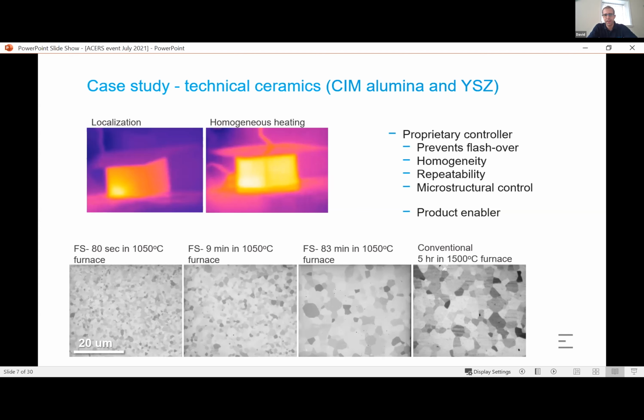But then if we start saying, we'll call it flash sintering, I suppose one could argue it's not flash sintering if you take 83 minutes, but in terms of the application of an electric field using our controller for 83 minutes at a furnace temperature of 1050, we get a comparable microstructure to the conventional one again, and that's consistent across the breadth of the sample there. Then as we go down to 9 minutes or even into that seconds regime, 80 seconds, we start to see that this density can be achieved, but you can retain a much smaller grain size for fully dense samples.